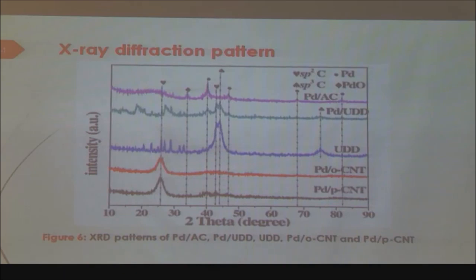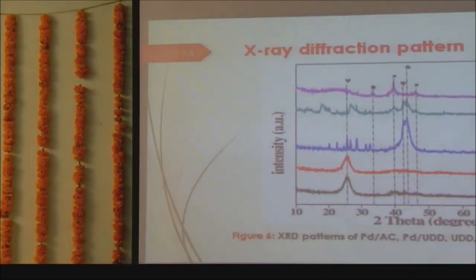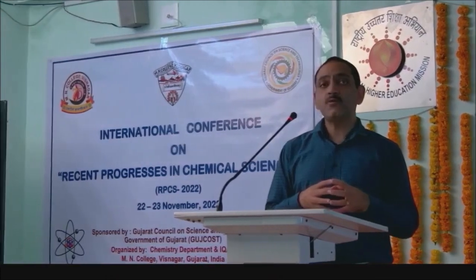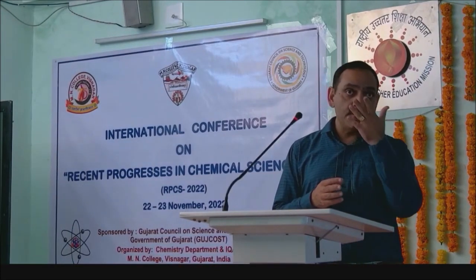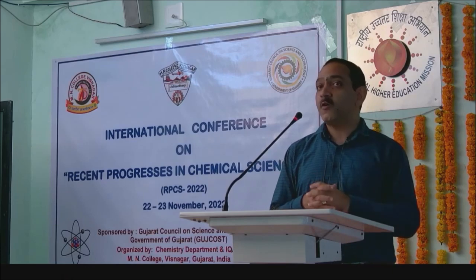So really getting no oxygen on your catalyst surface is a very challenging task, or you have to be patient. In the initial years of my research, when I did this, sitting in the lab for maybe 24 hours is a very tiring task, and you think, oh, my reaction is done, it should be cooled very fast, and you remove it. But just by making one mistake, not waiting for 1 hour, you get palladium oxide. So again, I'll say, if you are going into research, be ready to spend a lot of hours. I'm not discouraging, but the basic thing is that you should always be ready to spend maybe 10 hours, 12 hours, or my longest reaction that I have performed, which is 40 hours.